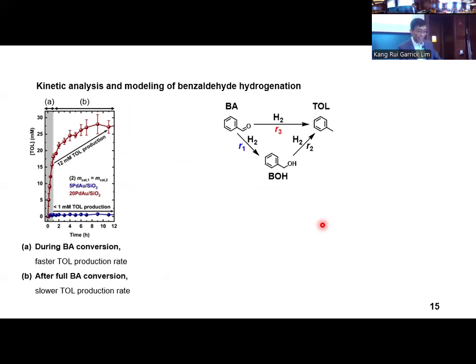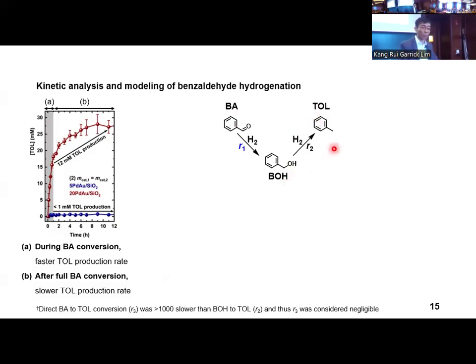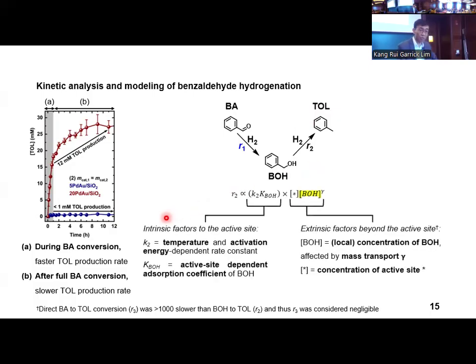We then performed some kinetic analysis and elucidated that toluene was produced in 2 phases. Toluene production during the active benzaldehyde conversion phase in the gray region here was very high and cannot be solely explained by the conversion of free benzyl alcohol into toluene. Our kinetic analysis also revealed to us that the direct benzaldehyde to toluene conversion was much slower than that of benzyl alcohol to toluene. Hence, we modeled toluene to be produced primarily from benzyl alcohol with a rate R2 that depended on factors both internal to and external to the active site.